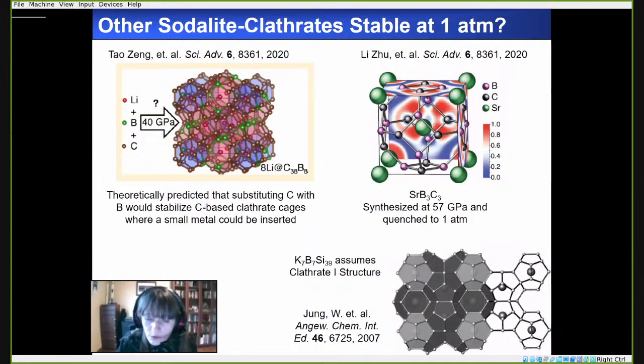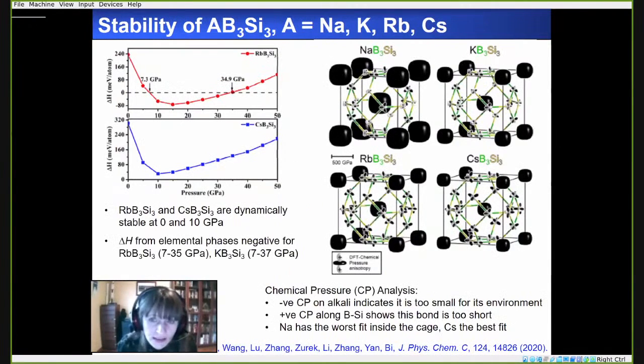Are there any borosilicides that could have these types of clathrate cage structure, which is very different from the borosilicides that have been made in the past? For example, this clathrate 1 structure prior to our work was the only borosilicide that was known. So we did theoretical calculations on various borosilicide cages, doping with different types of alkali metal atoms. And we took a look at their stability as a function of pressure, both thermodynamic and dynamic stability.